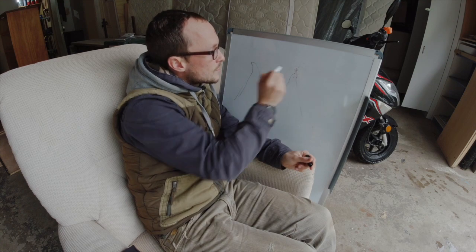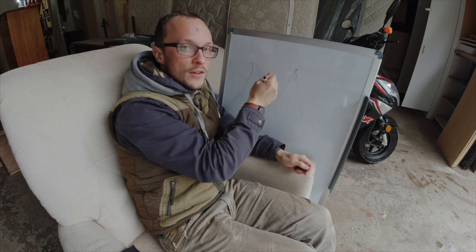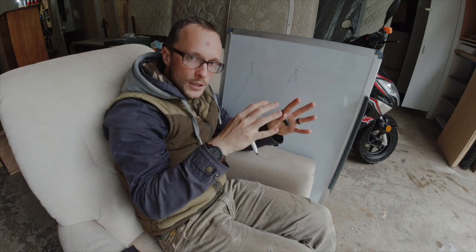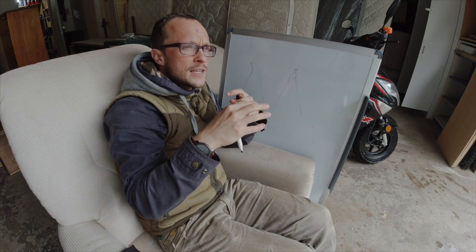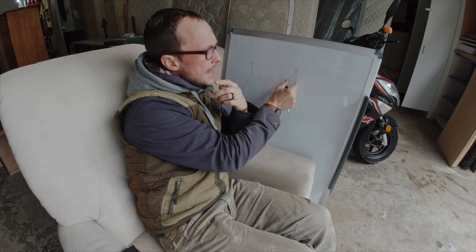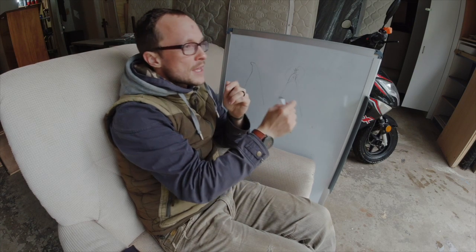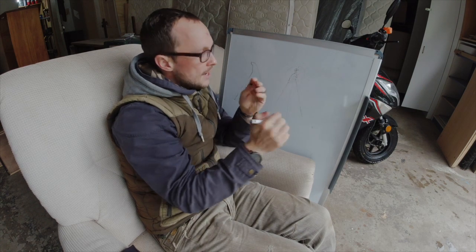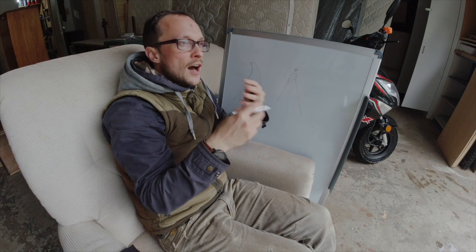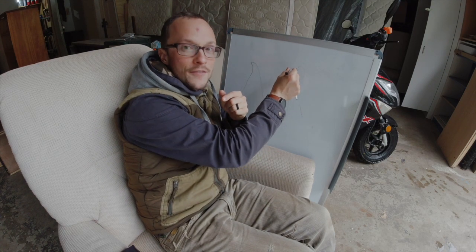This large burr is made of undamaged steel but sits outside of the regular triangular sharpening area of the edge. When it's stropped, the stropping has basically removed most of the small burr but left intact this large burr section. So essentially I've created a large burr, realigned it with the center of the knife, then removed most of the small burr — creating a sharpened burr, like an edge on top of your edge. As you wear down this large burr, the thickness remains the same for quite some time before it reaches the triangular sharpening area and begins to widen, which is why even after this edge has been dulled it can still cut like a pretty fine edge for some time.